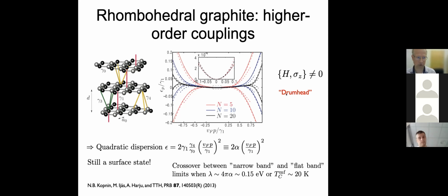This is because these other couplings, especially gamma 4, break the chiral symmetry of the Hamiltonian, and as a result, instead of the flat band, you get drumhead surface states in this kind of nodal line. Nevertheless, it's almost flat, a very, very narrow band in this case.